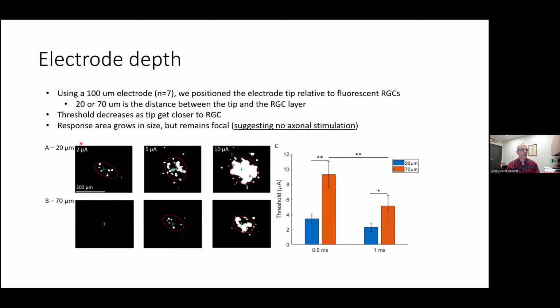We're able to show that when we have the electrode tip 20 microns from the retinal ganglion cell layer, we get a response with 2 microamps of current, which is quite low. And it increases in a way that suggests we're not activating axons, though I will say in some cases in this position, we did see axonal activation. At 70 micron distance, it requires more current in order to generate similar responses. So this is the measurement of the threshold, and we show that by being closer to the retinal ganglion cells, you achieve a lower threshold.